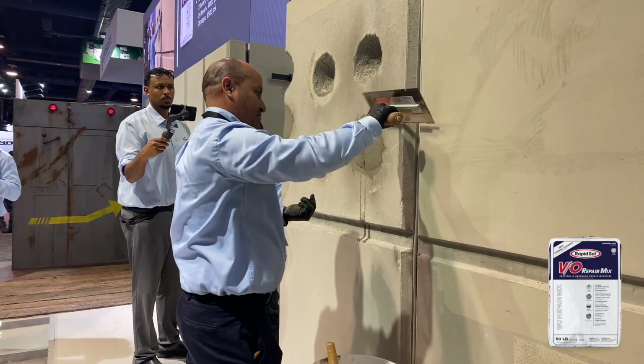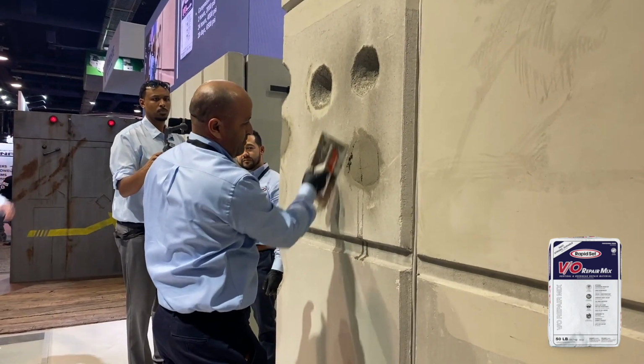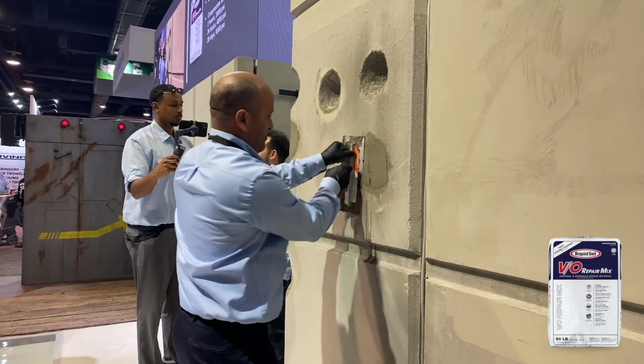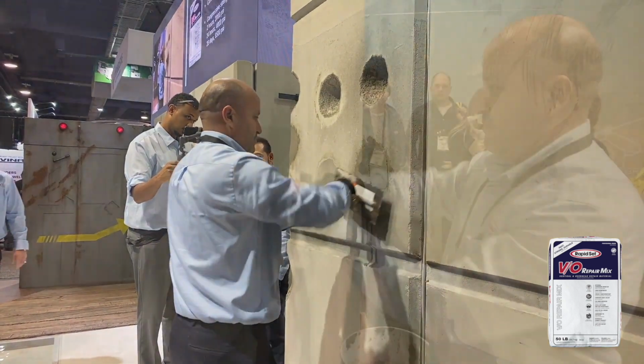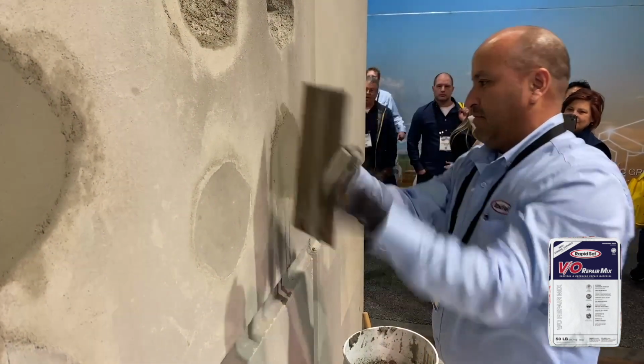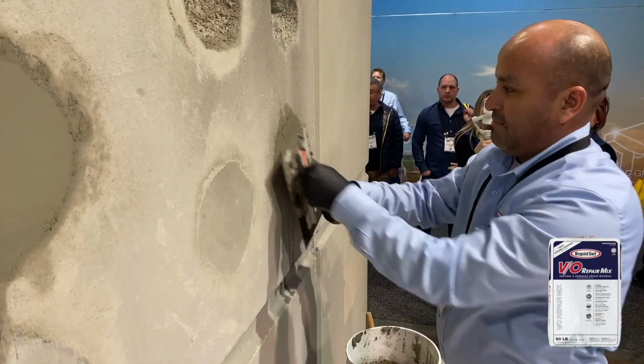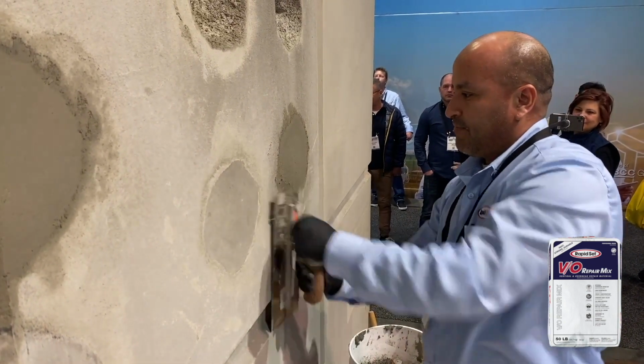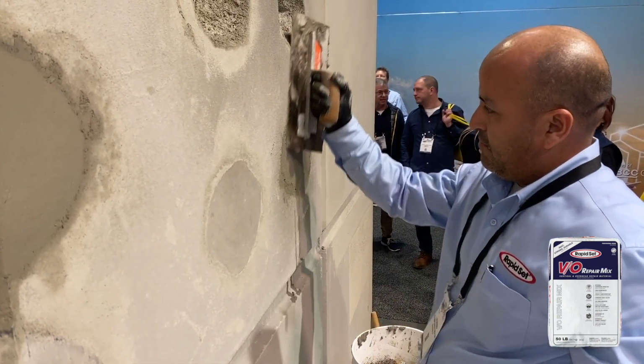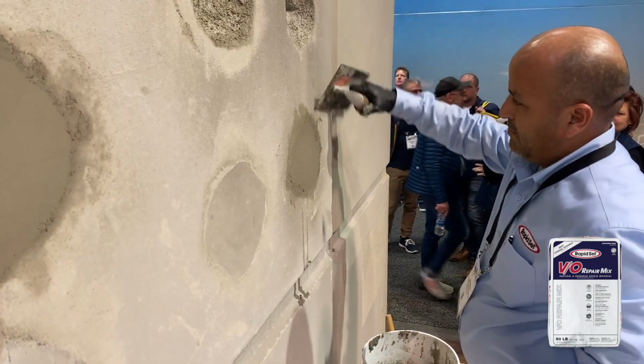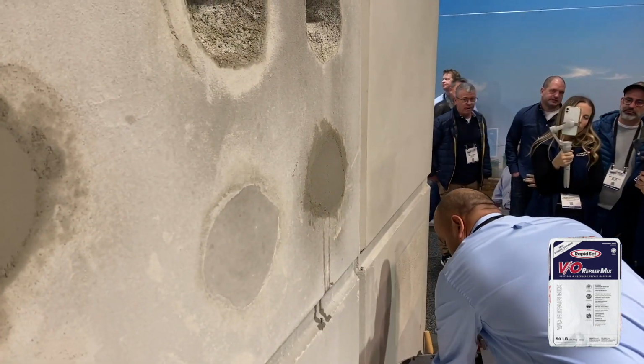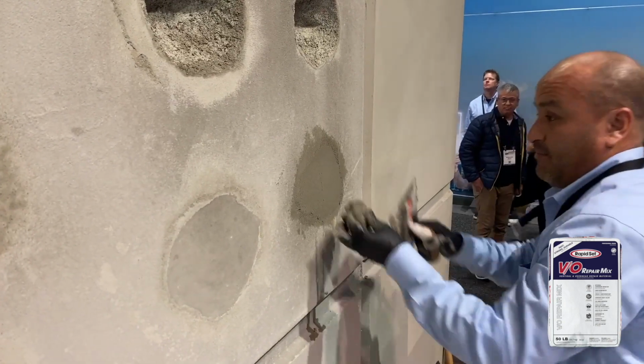So we get a structural strength in 2 hours of 2,000 PSI and 6,500 PSI at 28 days. Again, all these products are based on the Rapid Set CSA cement. It's a standalone cement that gets high early and long-term strength.